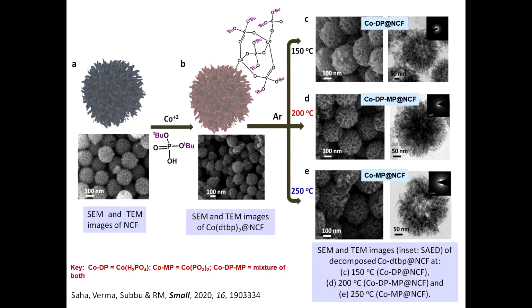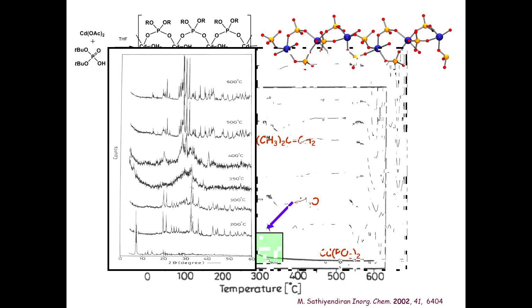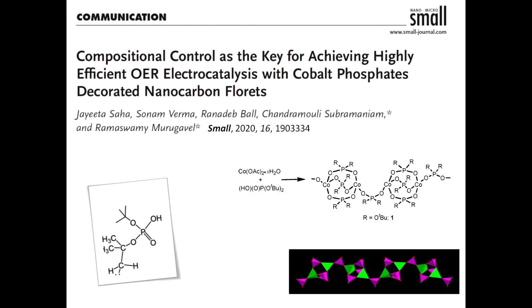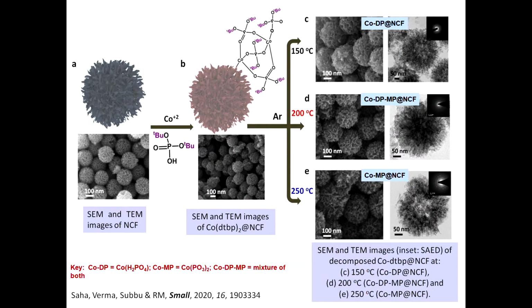Now in this, we essentially do this cobalt phosphate formation reaction. Instead of doing it in the flask, we did it inside this carbon nanostructure. So this is your pure carbon. This is the carbon with cobalt phosphate. I'm just presenting in not the same order as we got the results, because we were following the TGA as the guiding principle, decomposing the compound at 150 degrees centigrade, and then at 200 and 250. We were looking at the catalytic behavior of this material decomposed at different temperatures. Sorry for this non-standard abbreviation: DP stands for dihydrogen phosphate, which is H2PO4, and MP stands for metaphosphate, which is PO3.